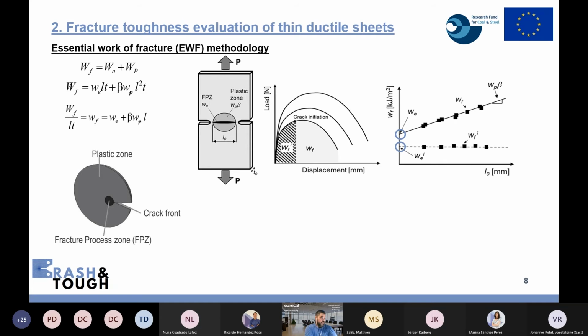The method is quite simple. You only have to test. You can use any kind of fracture mechanics test specimen, but in this case we use DENT specimens, or double-edged notch tension specimens, because they are simpler and also facilitate the test. You need specimens with different ligament lengths, which is the distance between the two cracks, and you test them up to fracture and calculate the fracture energies.